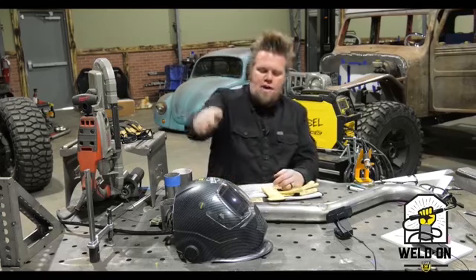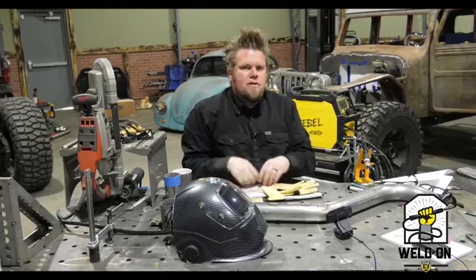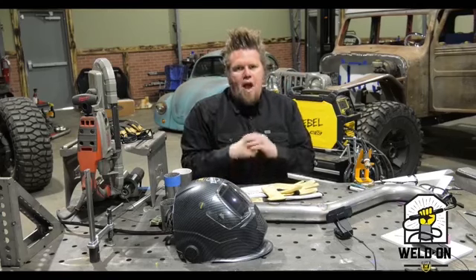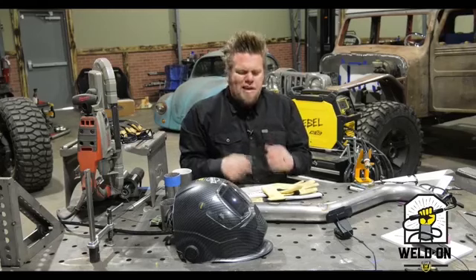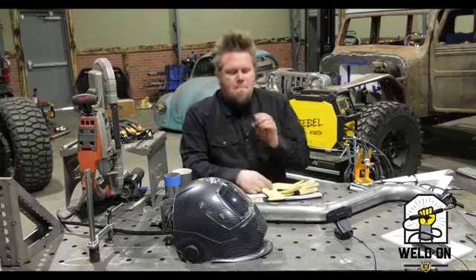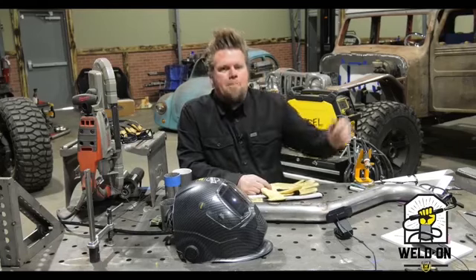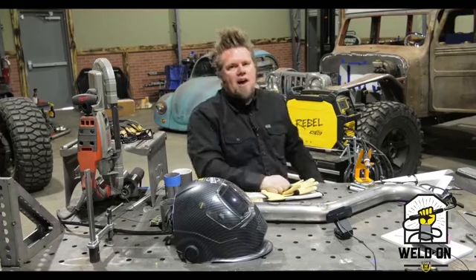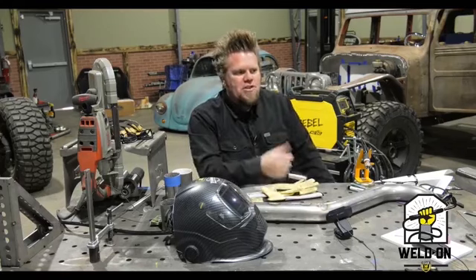I would not try and run all the way around the stainless pipe without the ability to have a foot control. Just because without that foot control, the minute that this blows out, it blows out like that and both edges tear off and then you just end up with a big hole and then you're chasing that hole.